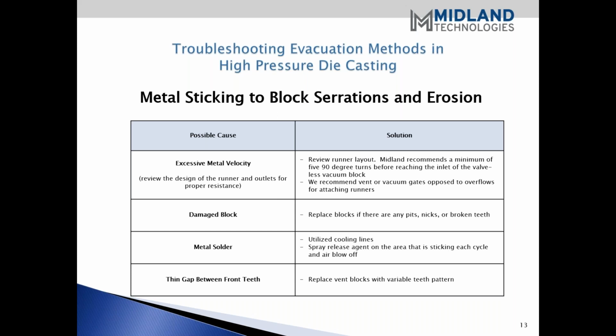We know, and physics tells you, that if you go from a large area to a small area, you're going to accelerate whatever the material is that you're flowing through those passages. And that occurs when you go into a large overflow and then come off that overflow with a small vacuum runner. We've seen dies that, as I mentioned before, were eroded to the point that there were grooves in the runners so that the runners were sticking. Obviously an indication that high velocity of metal was the culprit in that case.